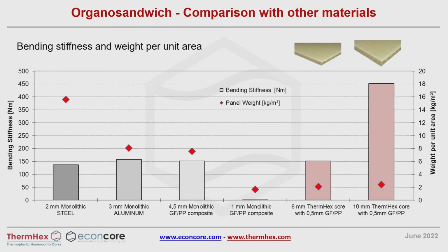So if you look at the material properties of such an Organosandwich, we see here a comparison between 2 mm steel and 3 mm aluminium and 4.5 mm UD cross-plied laminate of glass fiber polypropylene. So they have all about the same bending stiffness, and the steel has here about 16 kilogram. If you go to the right side, you see 16 kilogram per square meter, and aluminium and the composite are both about half, with 8 kilograms per square meter.